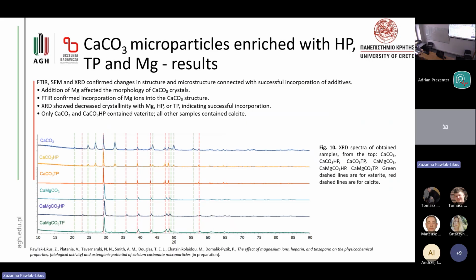FTIR and XRD analysis confirmed structural changes that were connected with successful incorporation of additives. Addition of magnesium affected the morphology of calcium carbonate crystals, which we saw on the previous slides. FTIR confirmed incorporation of magnesium ions into the calcium carbonate structure, and XRD, which we can see here below, showed decreased crystallinity with magnesium, heparin or tinzaparin. The green dashed lines are for the vaterite phase, and the red dashed lines are for the calcite phase.